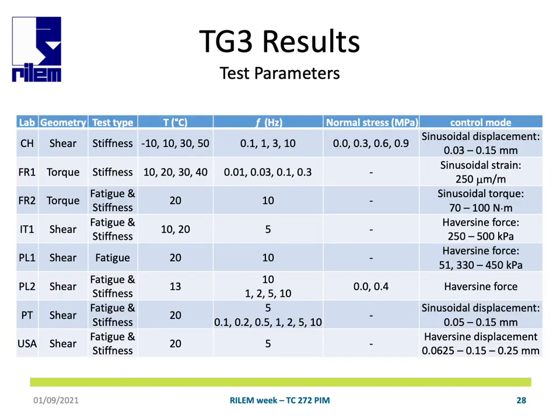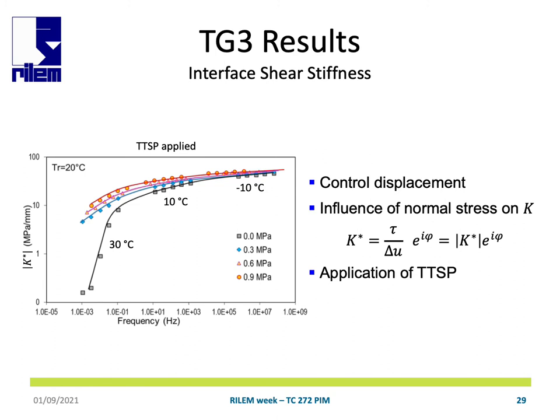This table shows the different loading conditions that have been applied in each lab. Temperature from minus 10 degrees to 50 degrees, frequency from 0.1 to 10 Hz, with also different normal stress applied. Some experiments are performed in displacement control mode, others in stress control mode. The different loading conditions allow to understand the effect of the normal stress on the interface stiffness measurement.